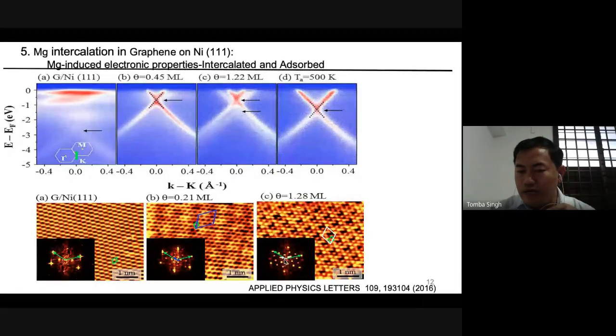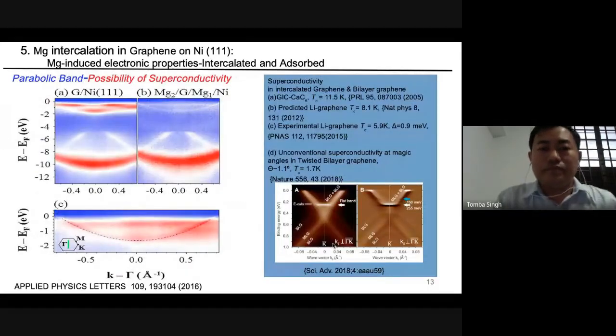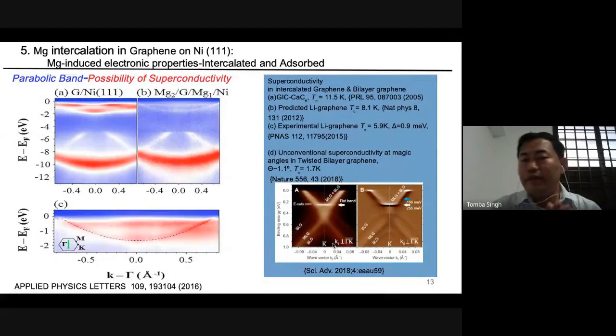This is indicated by these small white arrows in the FFT image, and the unit cell is drawn as a white box in this graphene topography image. So we can confirm that there are two types of magnesium location: above the graphene and below the graphene. This is the main result of this experiment. But before coming to the main result shown on the left side, let me share some literature survey.